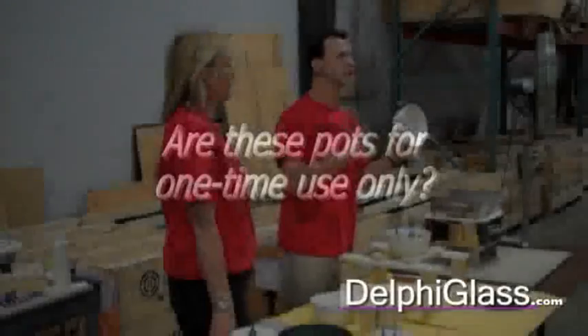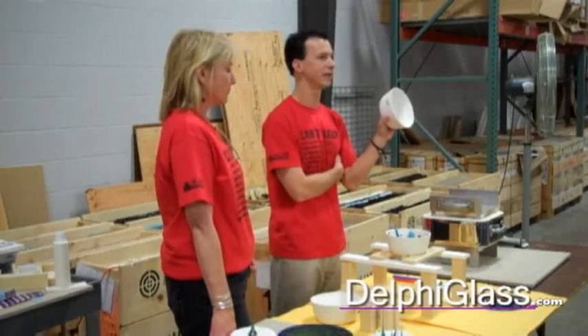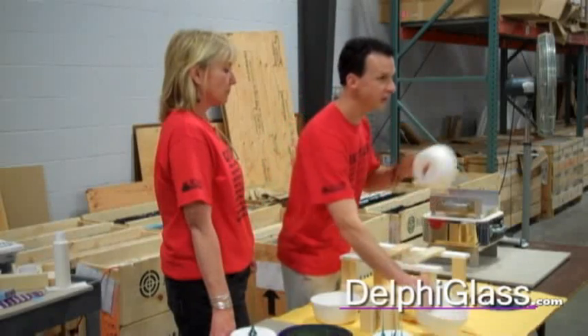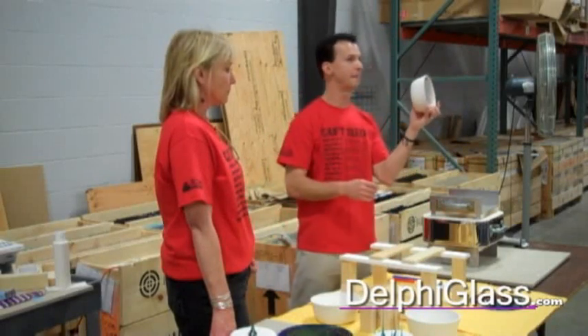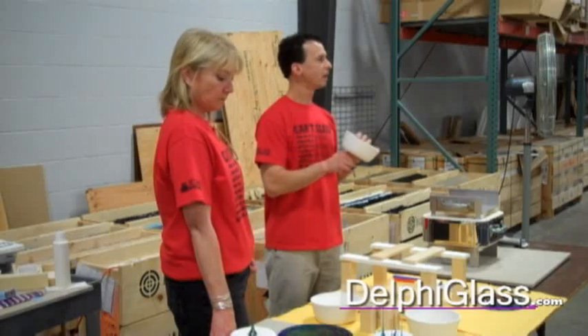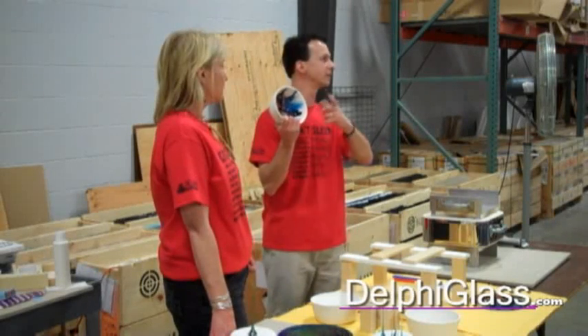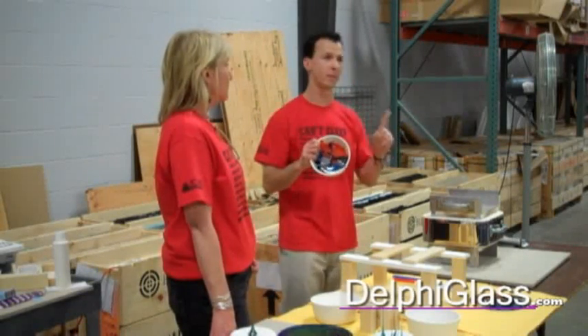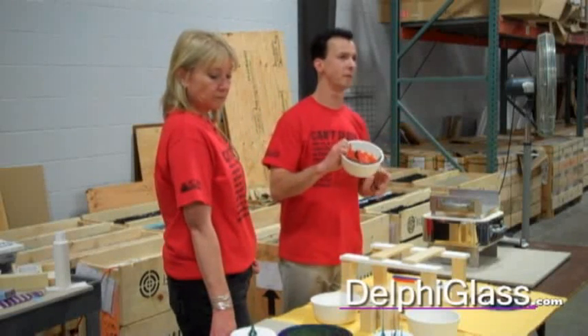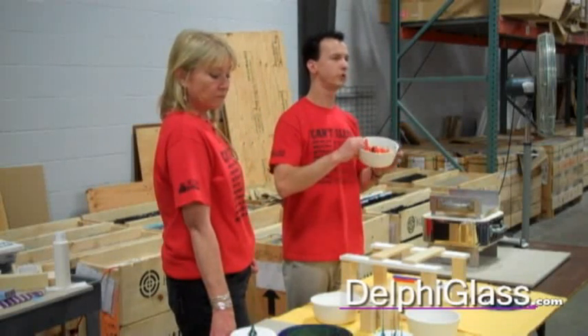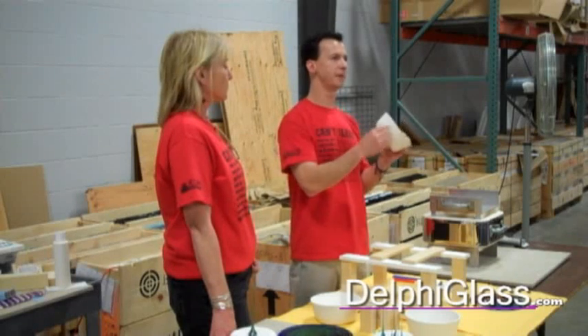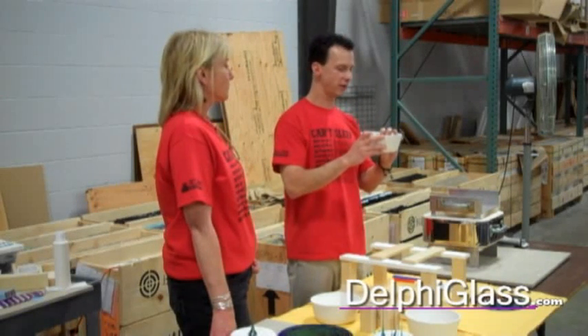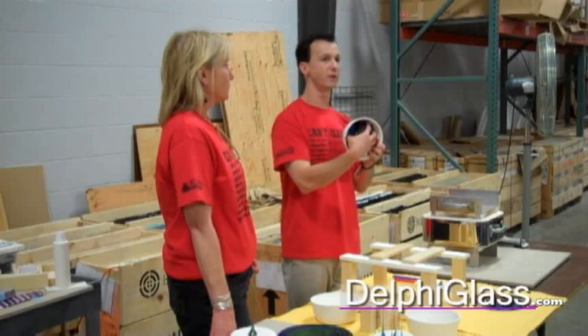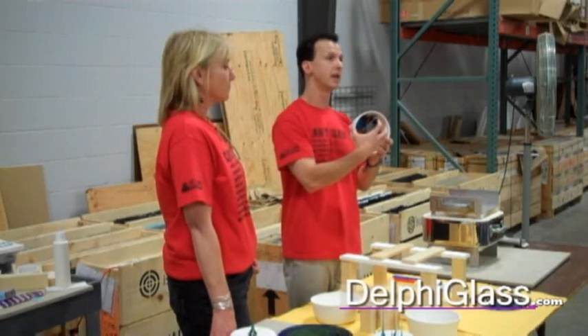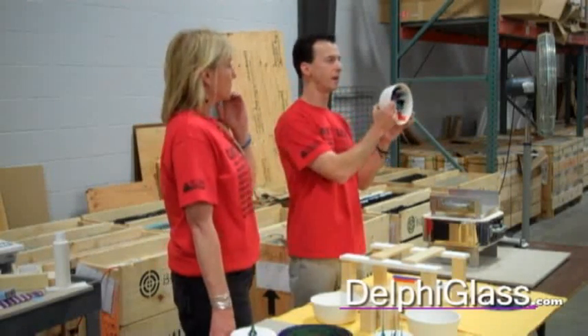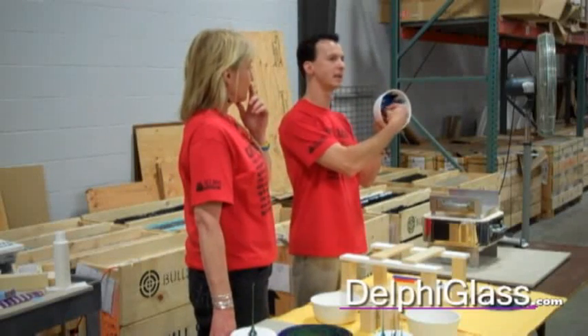Are they a one-use sort of thing? This particular pot I've fired 3 times, so they're not a one-use thing. People have cracked these pots in the kiln for a couple of reasons. One is that if you go too fast, you can shock the ceramic. The other issue, and I've noticed this more so, is that if you leave too much glass in the pot as it's cooling down, all the glass is cracked inside here.